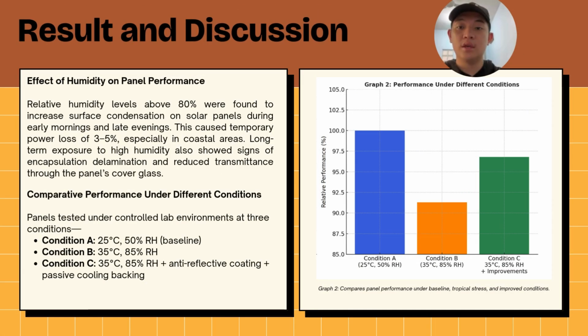So next is the effect of humidity on panel performance. Relative humidity levels above 80% were found to increase surface condensation on solar panels during early morning and late evening. This caused temporary power loss of 3 to 5%, especially in coastal areas. Long-term exposure to high humidity also shows signs of encapsulation delamination and reduced transmittance through panel cover glass.